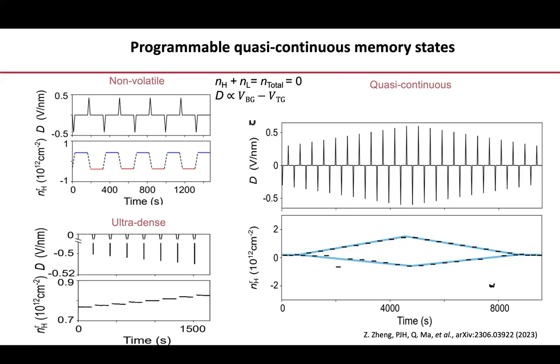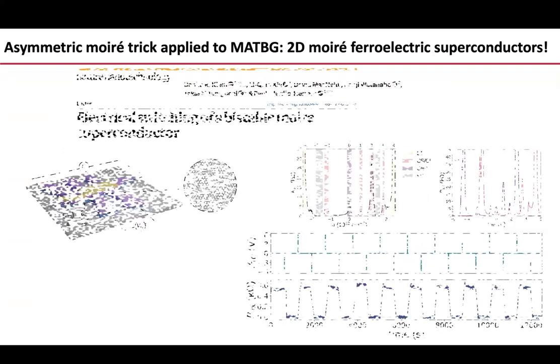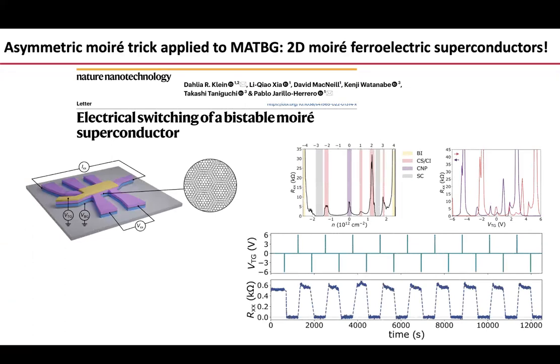Sorry. This trick you can do not just with bilayer graphene, but you can take now magic angle bilayer graphene, have one layer aligned to hBN and the other layer misaligned to hBN, and you can make a ferroelectric superconductor. A superconductor that switches in a bistable manner between superconducting and resistive states. And also the correlated insulator states switch in a bistable manner. And you do this by doing this trick. This was actually published a few months ago.